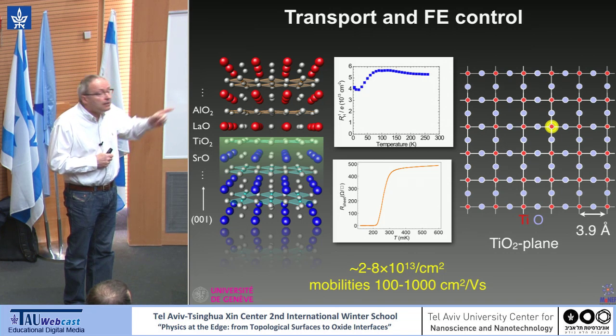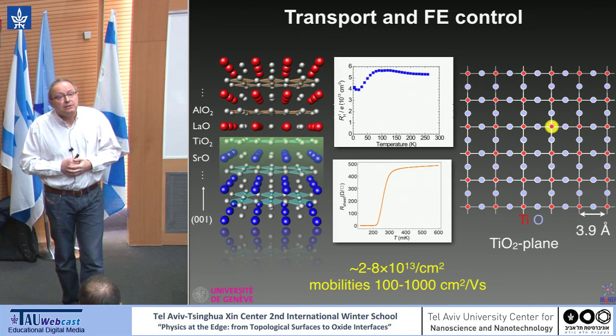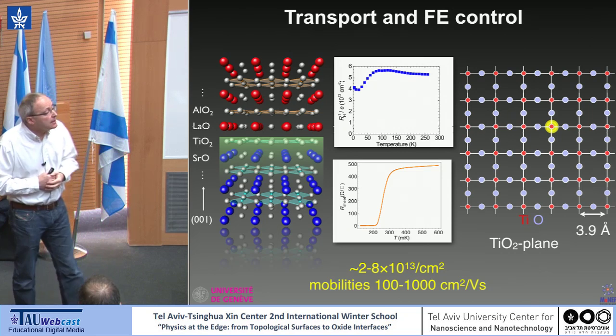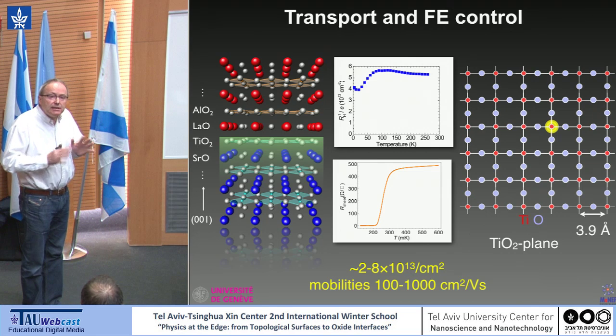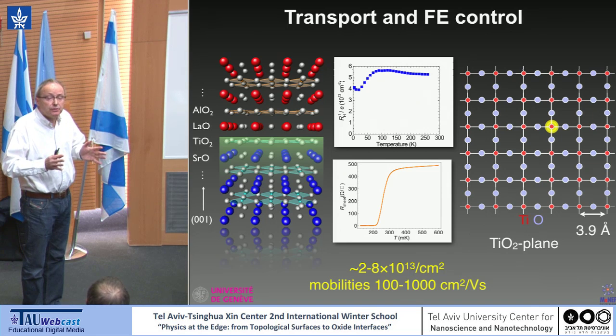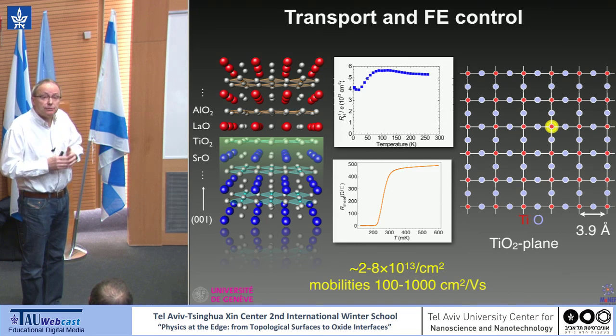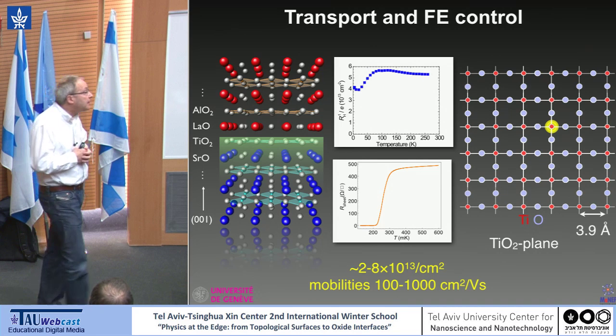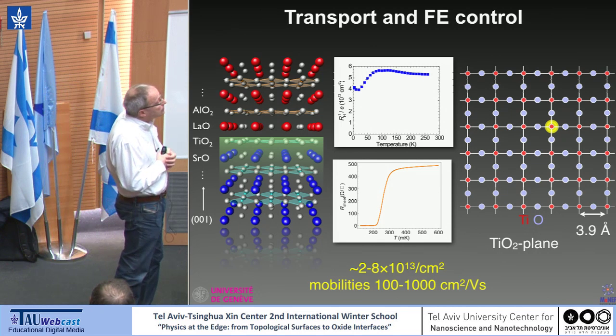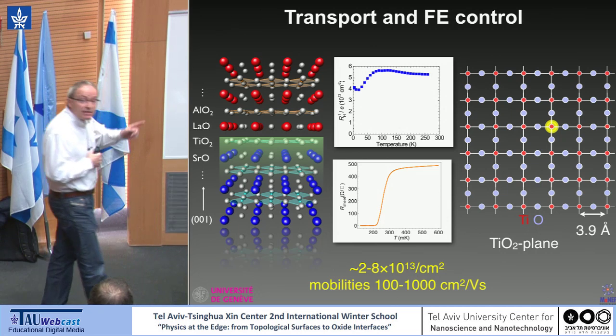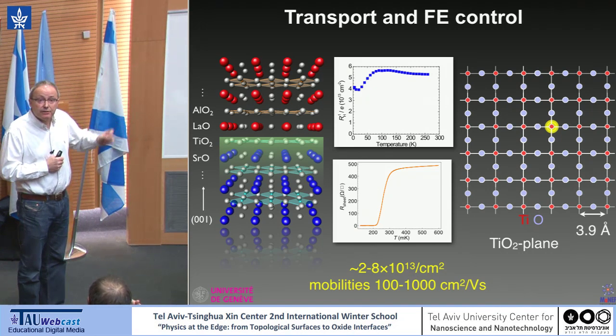And so here, we have 1 order of magnitude lower mobile carrier density. So we're not completely sure about this. We believe that the electrons are transferred, but maybe many of these electrons are trapped at the interface. And the mobile carrier density we see here is only 2 to 8 times 10 to the 13. Now, this is a very low carrier density.